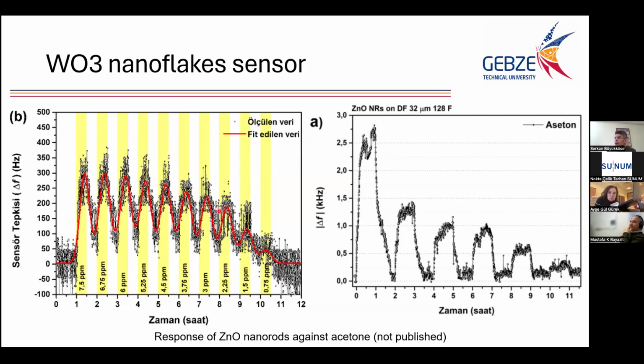But as you see, on the left hand side, you see the very small concentrations from 7 ppm to 0.7 ppm. On the right hand side, the level is a few hundred ppm. So it appears as a kilohertz shift in resonance frequency. You see here the shift is approximately 2.5 kilohertz, but for the small concentrations, it's a few tens of hertz. So this one is just for the acetone measurements.